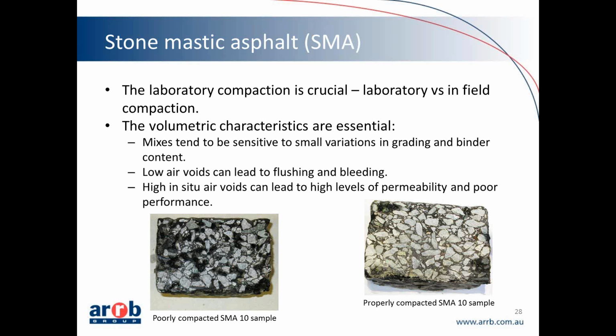SMA is quite sensitive. A small variation in the grading and/or the binder content can lead to low in situ air voids, which leads to flushing and bleeding on the surface, or on the other hand, another failure mode, a high in situ air void content that leads to permeability and really poor in situ performance. So this is why it's very important that in the laboratory compaction we are targeting an air void content and density which replicate the volumetric properties in field.